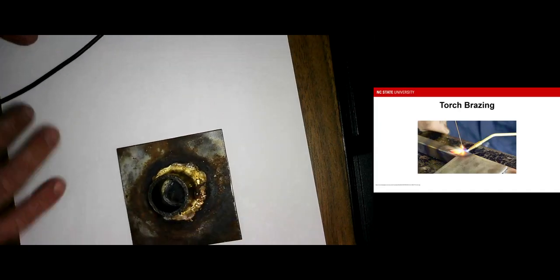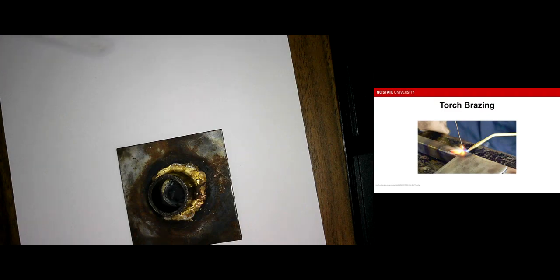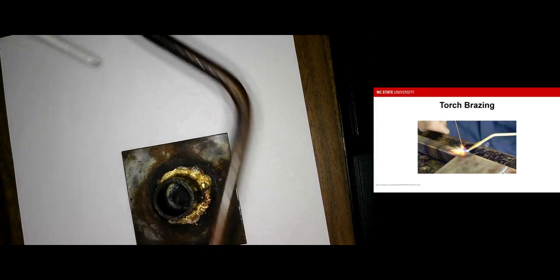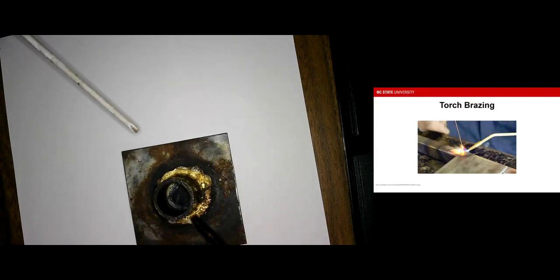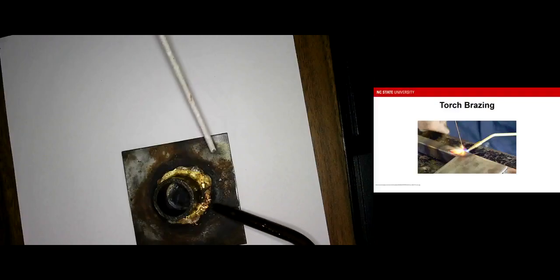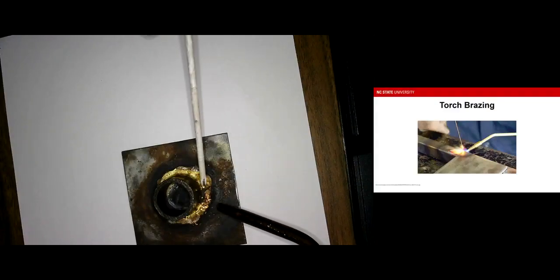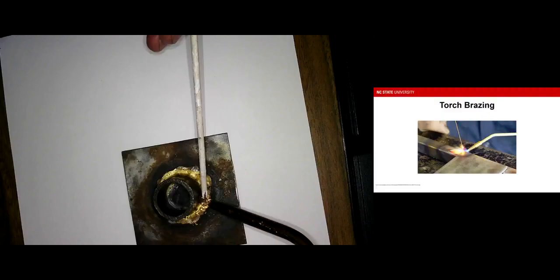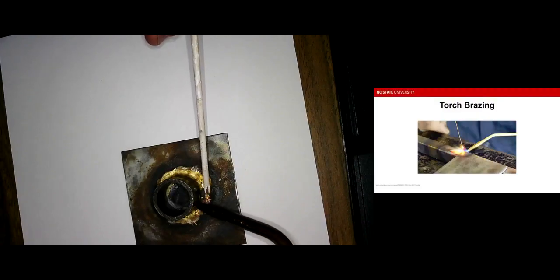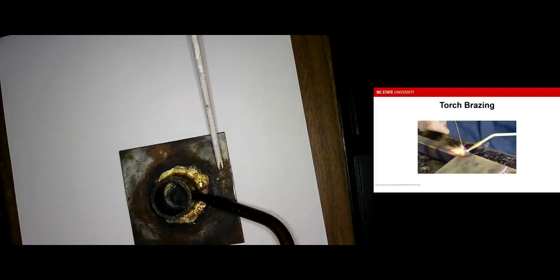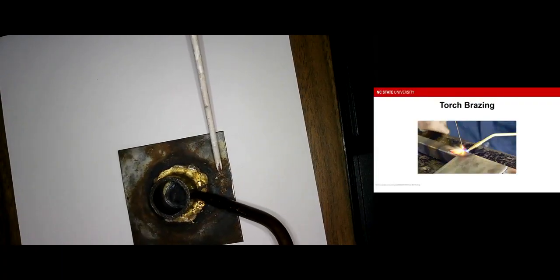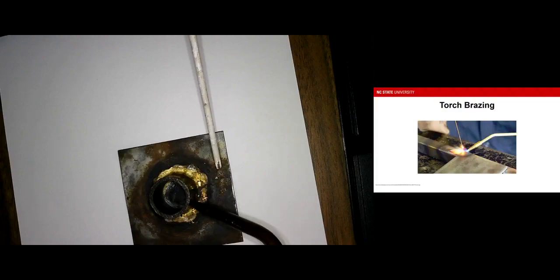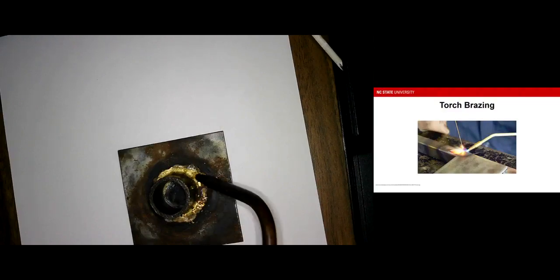Brazing is not as strong as welding, so the joint's a little bit weaker, but to be quite honest with you, it's very sticky. So what you do is you take your torch here, you'll have it hot, you'll have a flame, you'll heat up this pipe till it's almost cherry red, and then you'll slowly stick this rod into the inner cone. It will touch this metal, and it will run down and create a concave structure right down in here. So concave means that it caves in, and it should go down around all the way around this material. Again, if you have a big blob, you can then just kind of heat it up and move it around as necessary.